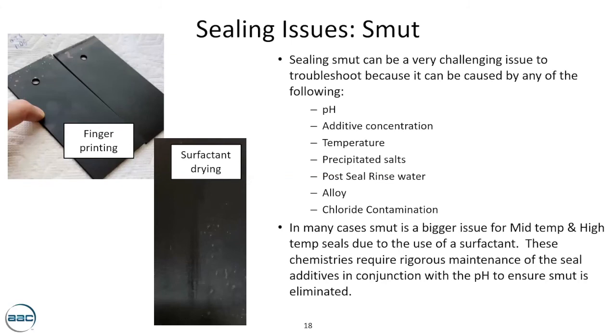Now we go on to the next slide, which deals with sealing issues. Troubleshooting sealing smut can be a very challenging issue because it is caused by various parameters such as pH, additive concentration, temperature, precipitation of the salts, rinse waters, alloy, and chloride contamination either in the rinse waters or in the seal tanks. In many cases, smut is a bigger issue, especially for mid-temperature and high-temperature seals, due to the use of surfactant. This surfactant is used to reduce the surface tension in the coating. These chemicals, especially the mid-temperature and high-temperature seals, require rigorous maintenance of the seal additives along with maintenance of the pH to ensure that the smut is eliminated.